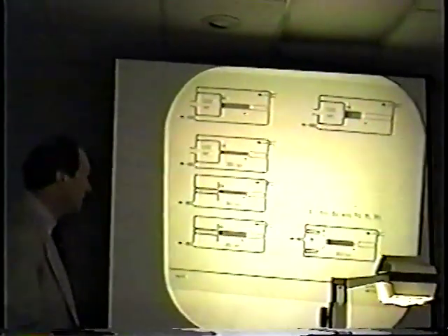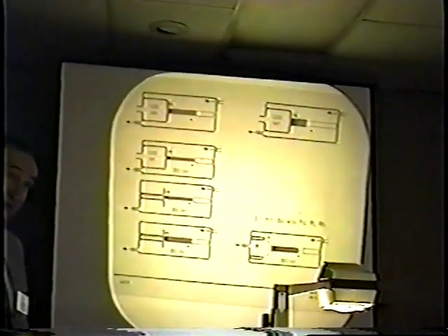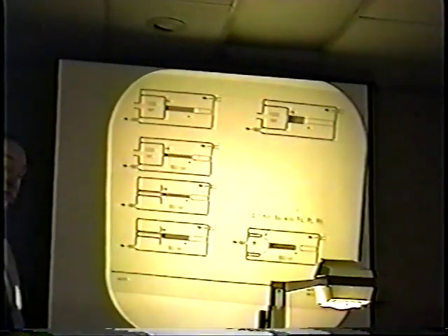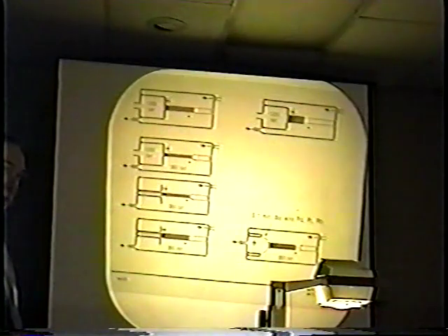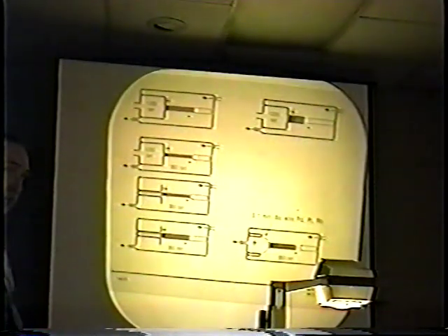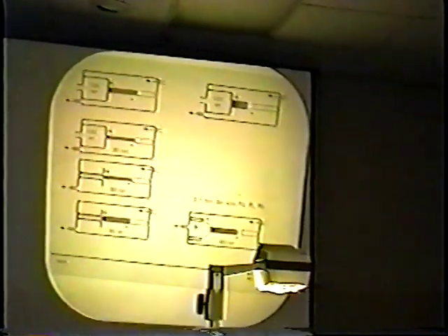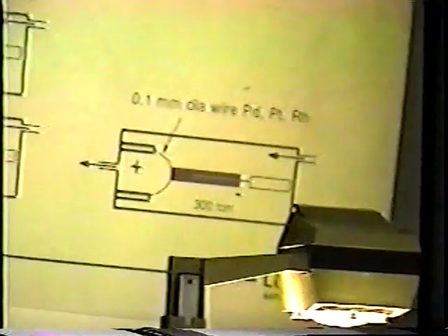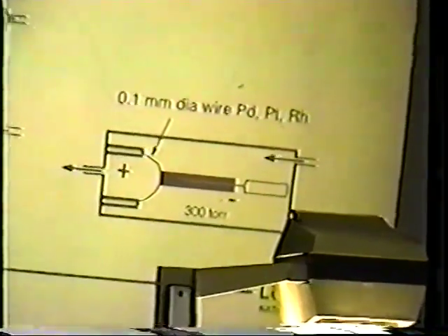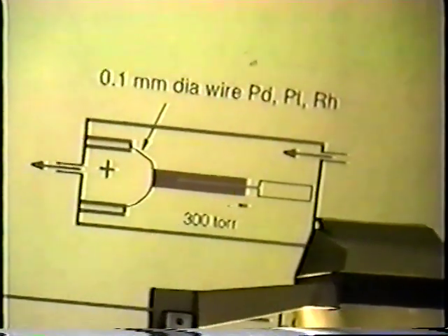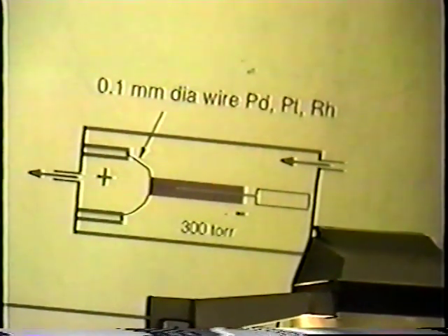The big advantage is that we have tried other geometries, and they're more difficult to fabricate. They use more material. This only needs 30 milligrams of this alloy, so we don't have to make a whole lot of the alloy. Also, this plasma, as indicated, only goes up halfway, so it doesn't touch any other material other than palladium or whatever this wire is. And that's a big advantage because we don't sputter all sorts of impurities.